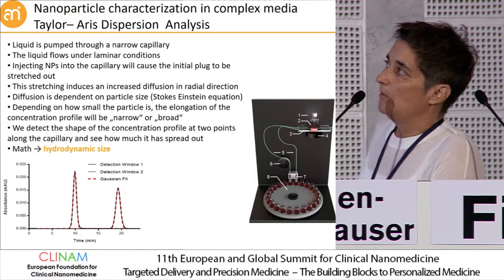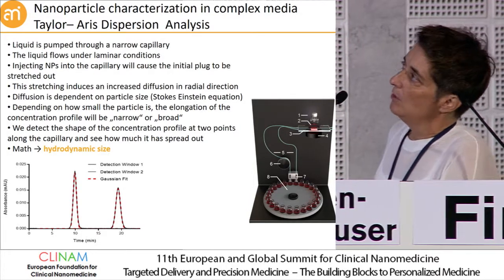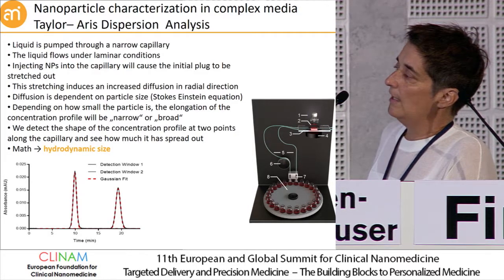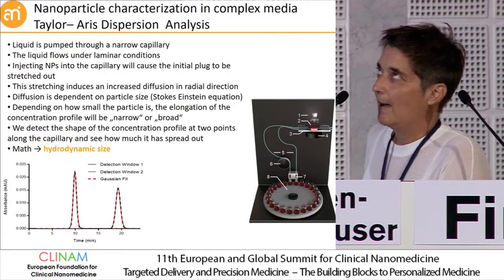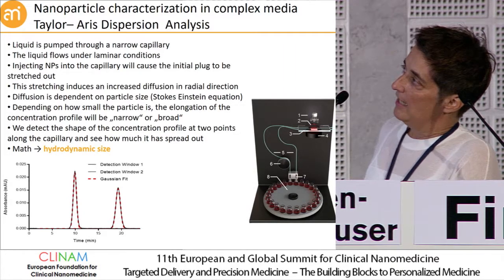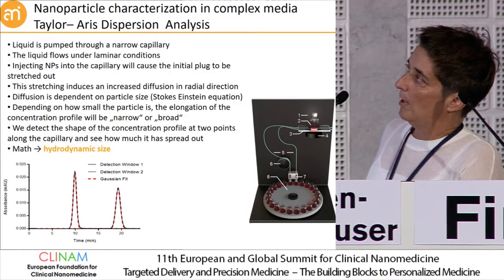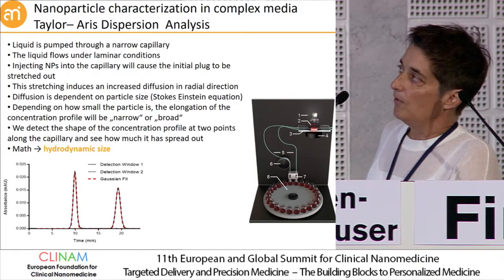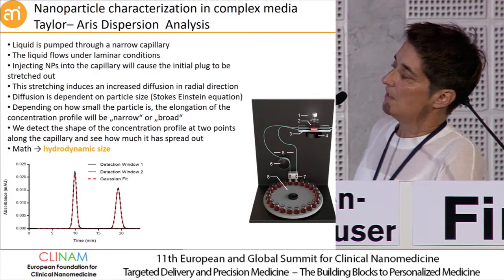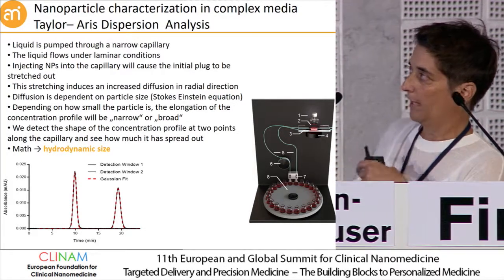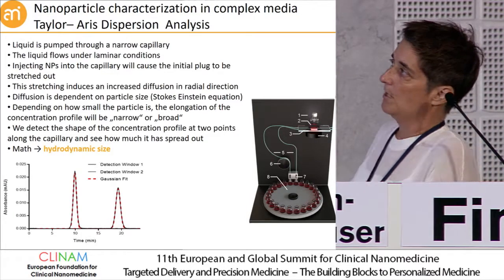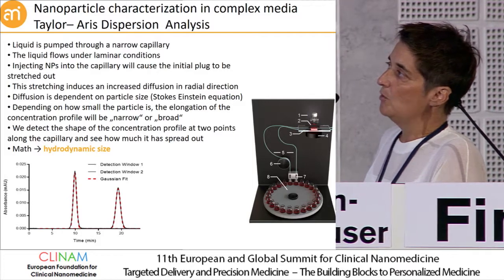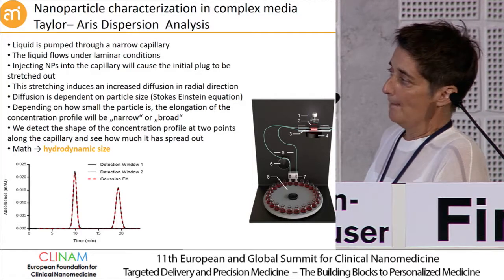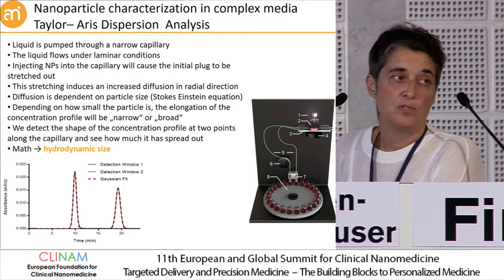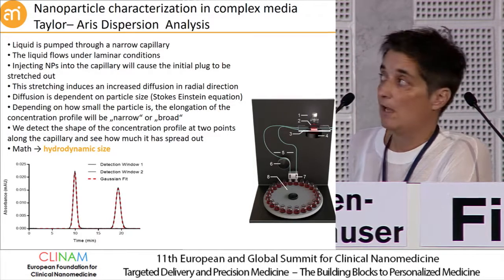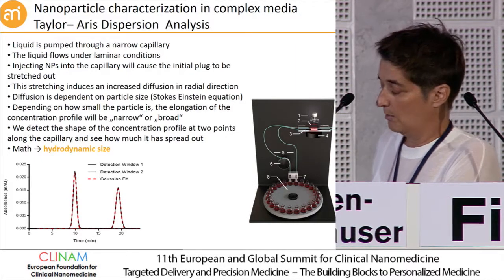What we've been starting to do in the last year is look at so-called Taylor-Aris dispersion analysis, using some sort of capillary electrophoresis setup. In essence, you have a liquid that contains the particles, you pump it through a narrow capillary, and the liquid flows under laminar conditions. In this laminar flow, the initial plug, where you inject the particles, is stretched out. You have a couple of detection windows, and essentially you measure diffusion again. This is something that chemists or biochemists have used for many years to characterize proteins, and we try to see what can be done with particles.